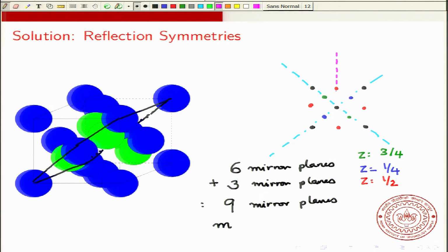So this was a mirror in the case of a cube, and the corresponding perpendicular one. So these were mirrors in the case of a cube. So this is not a mirror for the diamond lattice. So this is a mirror plane of the cube, but not of diamond. So these 2 mirror planes of the cube are not mirror planes in diamond. However, these 2 other planes shown in light blue, these are mirror planes.